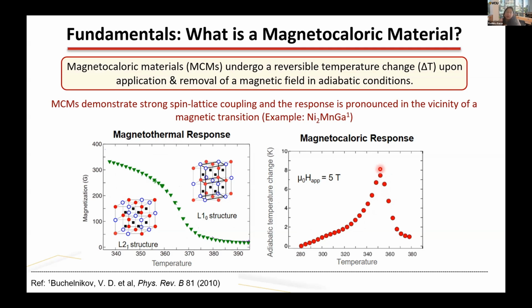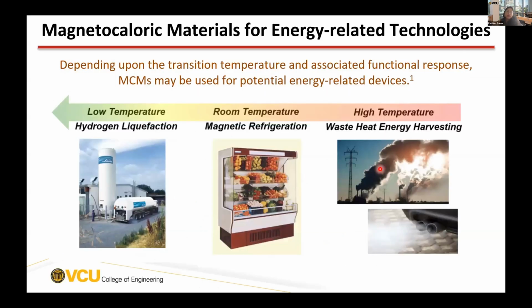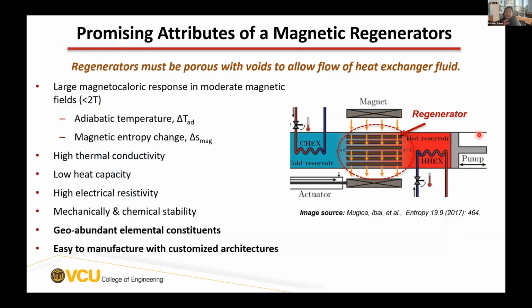Depending on the temperature at which we see this magnetostructural transition, magnetocaloric materials can be used for a number of potential energy-related devices. A magnetocaloric material that shows a low temperature magnetocaloric response can be used for hydrogen liquefaction purposes. Those that show room temperature MCE effects are of tremendous interest for magnetic heat pump devices, so magnetic refrigeration. And those that show magnetocaloric effects at high temperatures can potentially be used for waste heat energy harvesting. But regardless of what the material does, in order to realize its true potential, it has to be deployed within an active magnetic regenerator device, known as an AMR device.